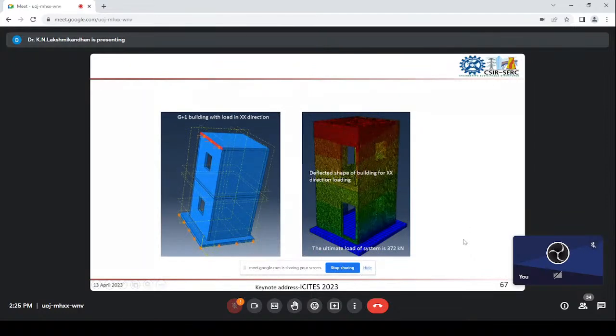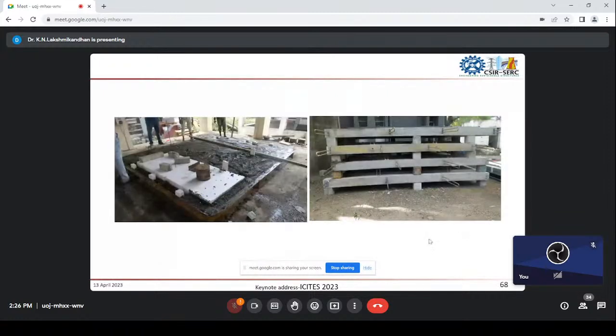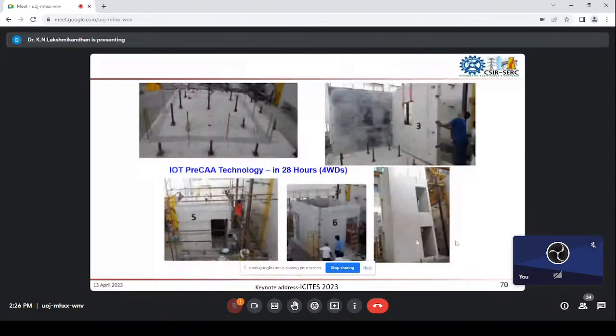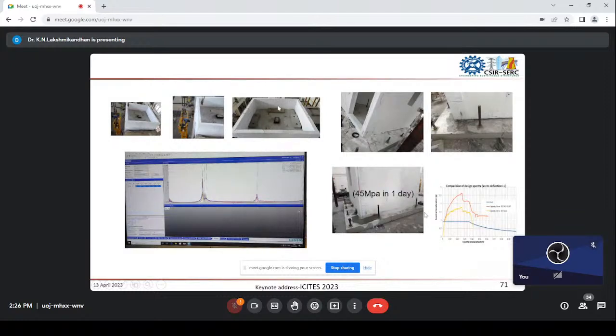In a similar way, we integrated the two stories and did the analysis, and we found that it is very useful for construction without escalating the cost, without compromising any strength characteristics, and without affecting the affordability for all groups. So this way we cast and transported, and this is the way we assembled the entire structure, which is G+1. We assembled it in 28 hours and tested it for lateral load. In a similar way we applied the actuators and exciters. We used exciters to find the stiffness of this structure, and the stiffness of this structure and of the solid concrete RC structure seem to be the same. As a result, the composite action we are getting is perfect, 100% composite action with perfect integration.